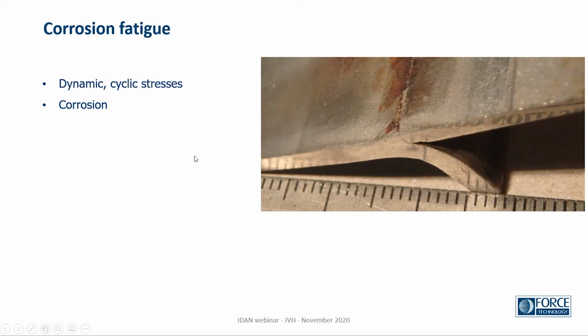And corrosion fatigue, I don't know if you can see it, but we have a weld here, and we have a fatigue crack running along this due to vibrations in this part. And as I mentioned before, fatigue is one thing, but when you have corrosion on top of it, it will initiate faster and grow faster.